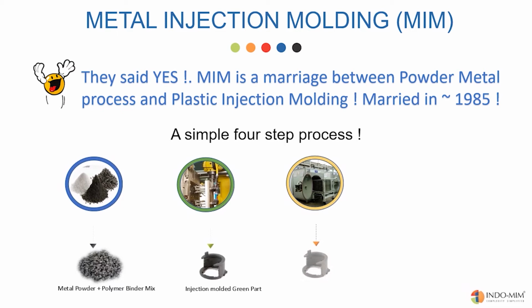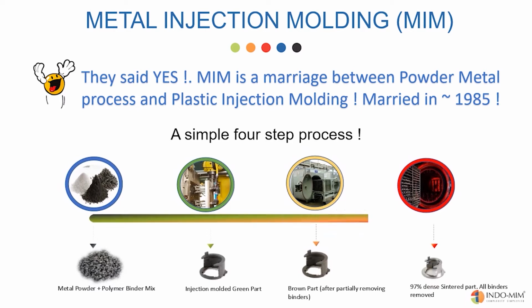Step 3 is to remove part of the binders. The process is called debinding. After this process, the components are called brown parts. The last step is to sinter the brown parts and remove all the binders added. During sintering, the high temperatures enable the metal particles to diffuse with each other to get to 97% minimum density. After the sintering, the components are 100% metal with no binder material in them. Hence, they display very similar material properties as corresponding wrought material. So, we made complex shaped metal parts without even getting anywhere near a metal cutting machine.